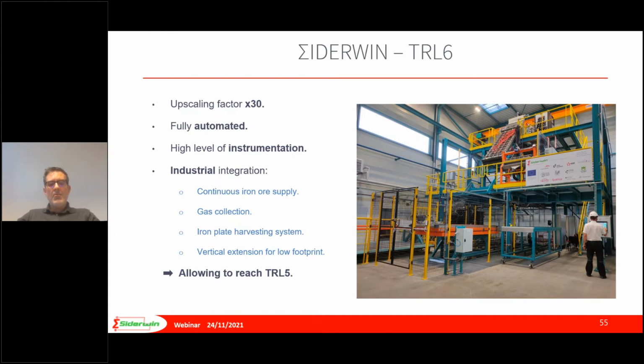And we were able also to define all the equipment that is needed for such an exploitation of the cell. I mean, we had to define the supply for the continuous iron ore supply, the device and the equipment for the gas collection, something which is important because, as you have already seen, at the end of the electrowinning process, we get an iron plate, which is deposited on the cathode, and that needs to be harvested safely. So we had to define a harvesting system to remove the iron plate from the cell. And we also have to take into account the footprint of such a process. So the pilot has a big vertical extension, so that in the future we should be able to stack different cells to limit the footprint of the equipment.